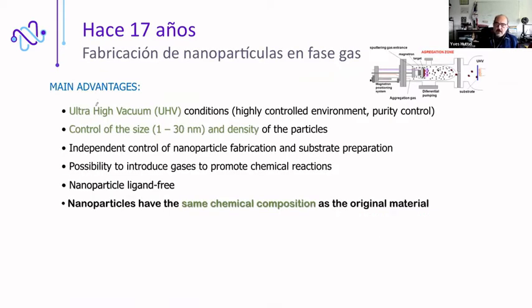These are the main advantages. First, we work in ultra high vacuum conditions, which means that we don't have impurities in the atmosphere where we create the nanoparticles, so we have very pure nanoparticles. The other advantage is that we can control the size of the nanoparticles from 1 to 30 nanometers, and we control the density of the nanoparticles we deposit on a substrate. The fabrication of the nanoparticles is independent from the substrate preparation, not like the case of my iron nanoparticles, where we had to heat the substrate to 1000 Kelvin. So we can deposit the nanoparticles on any substrate that is vacuum compatible.